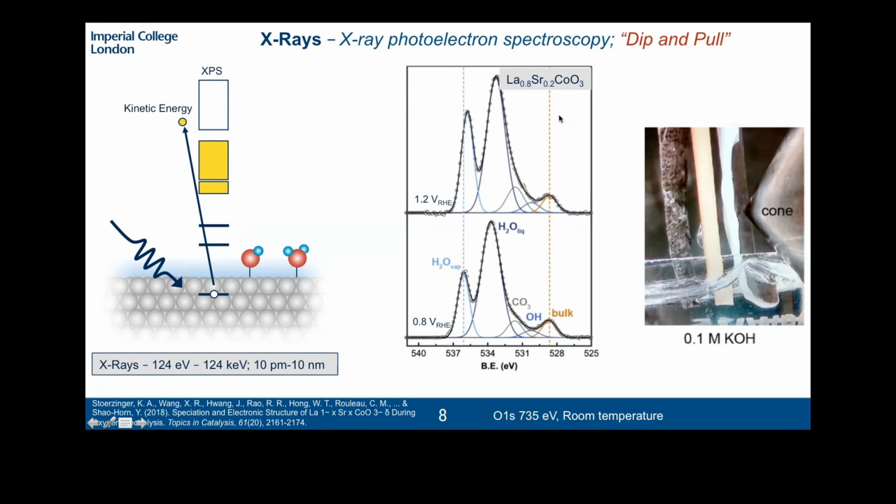But when you start seeing the spectra, one can then start appreciating how challenging this might be, because you have these huge peaks that come from water in the gas phase and water in the liquid phase, which can basically dwarf species like OH or carbonate, which also have oxo groups in them, and they might be really interesting from the perspective of trying to understand the reaction mechanism, but their intensity is now significantly lower because the spectra is dominated by peaks from water in the gas and the liquid phase.